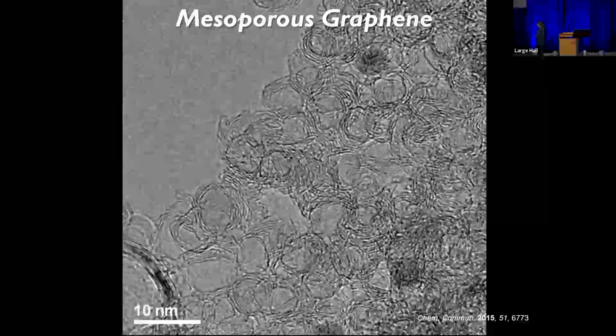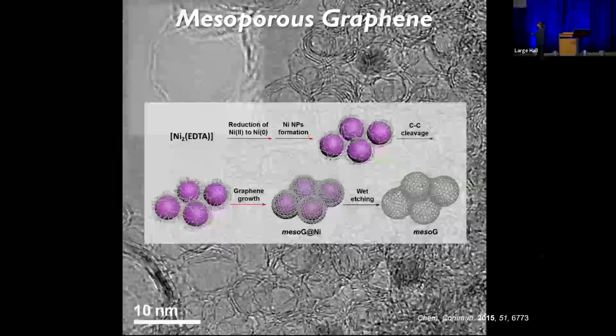Next example is that we can mimic the preparation of graphene by using the coordination compound. Okay, as you can see here, we successfully synthesized the mesoporous graphene, which has a highly crystalline structure. Okay, what we did in this study, we just selected nickel EDTA. Nickel EDTA is just a very simple textbook compound, right? But during the thermolysis, we could know that nickel zero nanoparticle is formed. And this nickel nanoparticle acts as a catalyst for C-C cleavage of EDTA. And also it can act as a catalyst to grow graphene on the surface. Then finally, we can obtain the graphene structure.